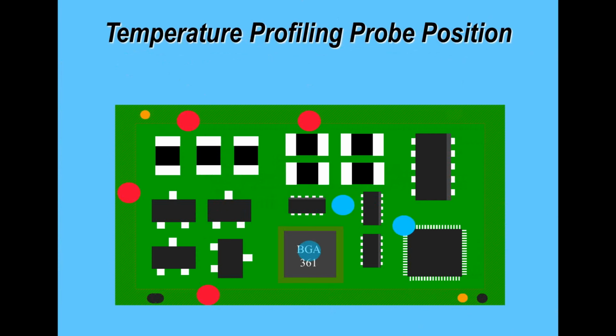The coldest bits would normally be somewhere in the center of the printed circuit board. It has a smaller surface area to absorb energy, and it's connected to a lot more surfaces. Underneath the BGA, even plastic BGAs, you will always find a slight difference in the temperature. So you need to monitor on the edge and also underneath the BGA if you're profiling the BGA specifically.